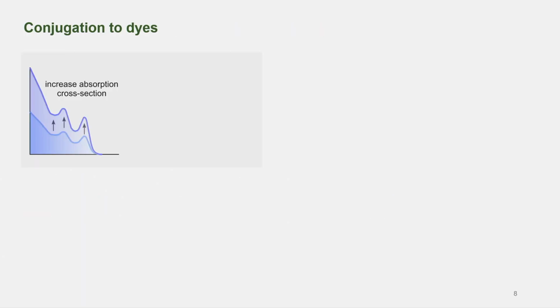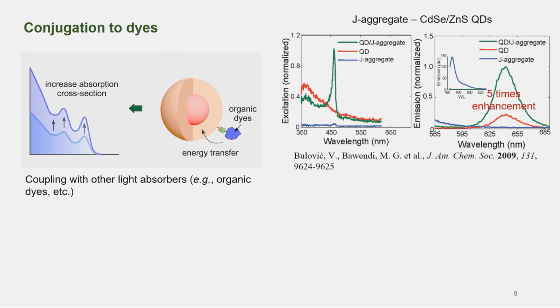So what do we think is the solution, or how to mitigate this? First, in order to increase the absorption coefficient, our first thinking is to conjugate some light absorbers. If you are careful about their spectral overlap, where the emission spectrum of the light absorber overlaps with the absorption spectrum of the quantum dots, you can have energy transfer between them, and this actually raises the absorption of the whole system. Actually, Bulović group and our group published a paper in 2009, bringing J aggregates in close contact with quantum dots, and this is the excitation spectrum.